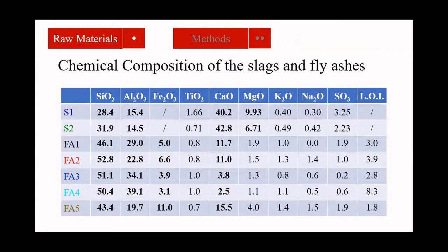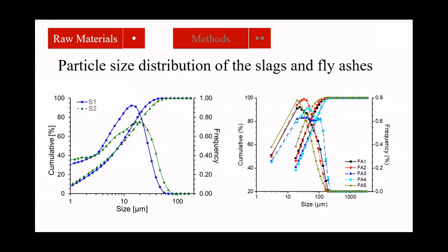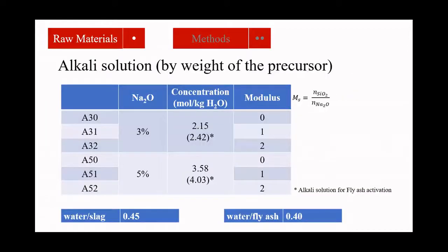I will just skip the introduction of the chemical composition, but in general, there are very typical chemical compositions for slag and fly ashes. The D50 particle size for the slag is around 10 to 20 micrometer, quite typical. And for fly ashes, the particle size is more coarse, more than 30 or 50 micrometer in D50. And I also use different alkaline solutions to activate the SCMs. For this pure system, it's easier to explore its mechanism, and I use a water to slag ratio and water to fly ash ratio of 0.45 and 0.4.